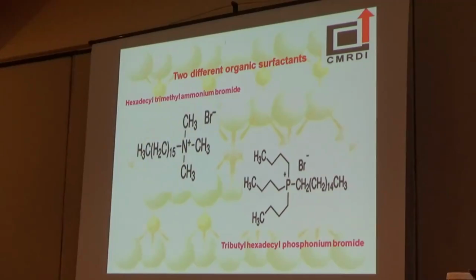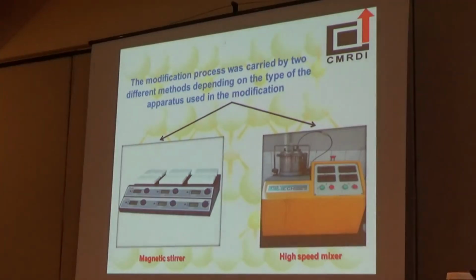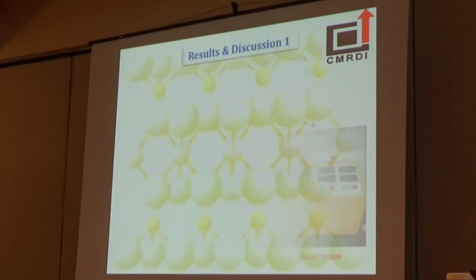Two different organic surfactants were used. The first one is hexadecyl trimethyl ammonium bromide, and the second one is tributyl hexadecyl phosphonium bromide. We used two different apparatus in the modification process: the usually used magnetic stirrer and the high-speed mixer, which is used for the first time in the modification.